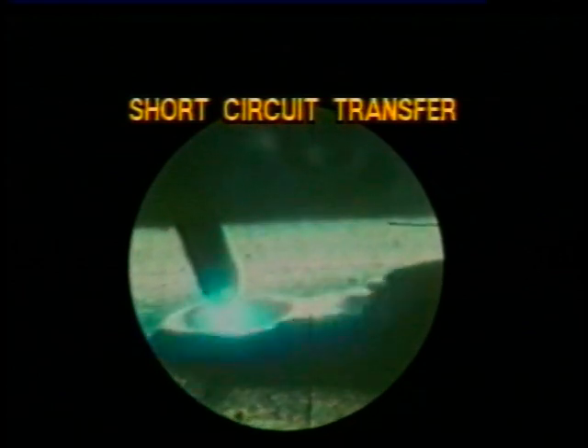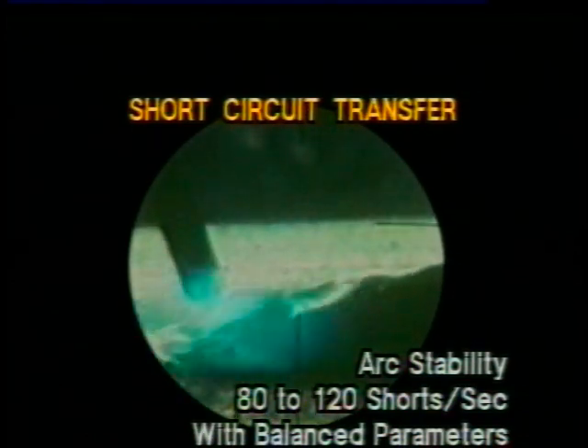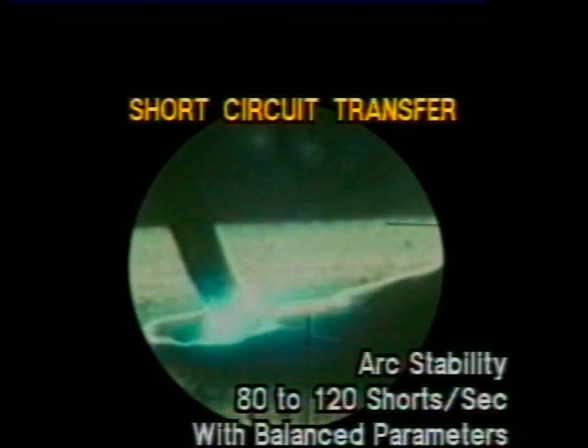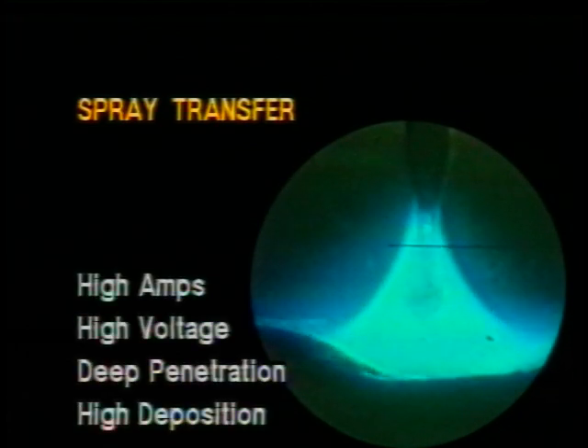Now with the short-circuiting, considered a low amperage mode of transfer in which the wire short circuits generally up to about 120 times per second. Then we have the high amperage spray type transfer in which the wire doesn't short circuit and it's generally over 200 amps. Deep penetration, high deposition.